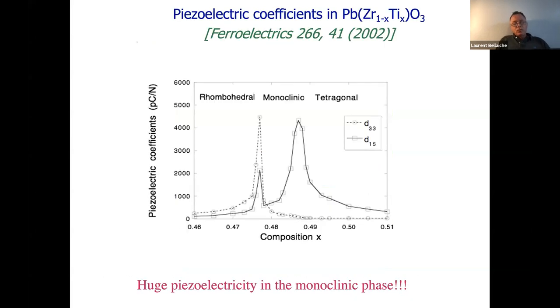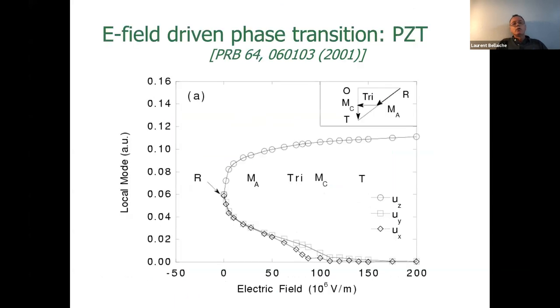And then you say, okay, why not stop here? Let's go to piezoelectric coefficient versus composition, looking at this d33 and d15. And we find that in this monoclinic intermediate phase, a huge response. We're talking about 4,000, 5,000 picocoulomb per Newton. You can also put an electric field into your simulation, as I told you before.